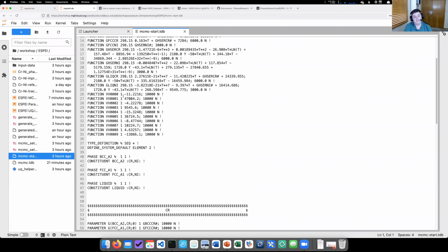And so my suggestion would be that if you want to compare different parameterizations, different models, anything, you just do two or more ESPEI Markov chain Monte Carlo runs, and then you can evaluate the uncertainty. And then for whatever your metric is, whatever your observable is, maybe it's a particular phase boundary of interest, or maybe your data, there are well-defined statistical techniques for how to take the Bayesian quantified uncertainty and compare two models to each other.